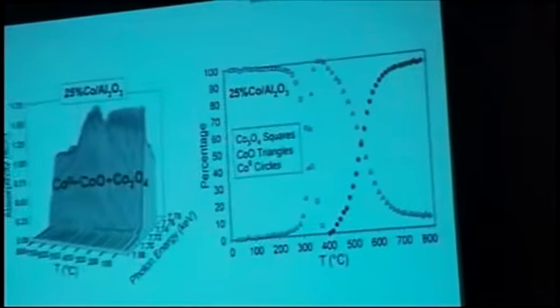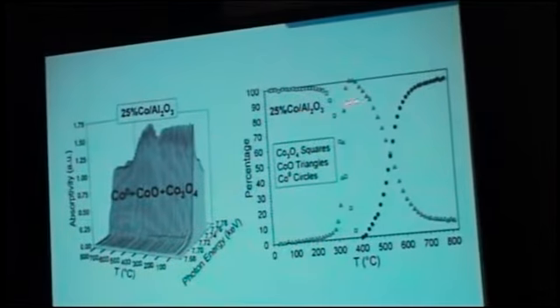In looking at 25% cobalt on aluminum, essentially, you can go back and forth. There's no real effect of going from 15 to 25%. You essentially have the same curve, and sets of curves. You're talking about 590 or relatively high temperature pretreatment being necessary in order to make a good active catalyst. Now, our challenge with the reactor is we're limited to 400, 425, 450 degrees C, and the comment was, well, wait longer. Well, we waited 6 hours, and no, it wouldn't seem to work.